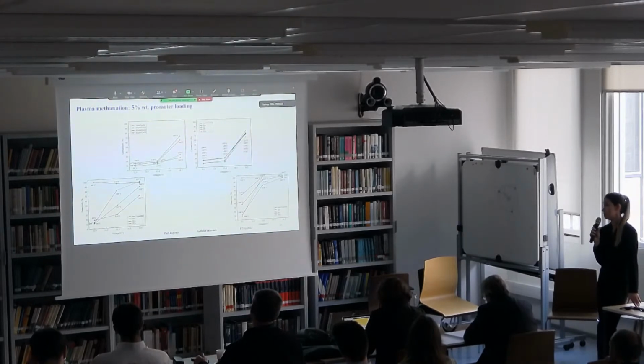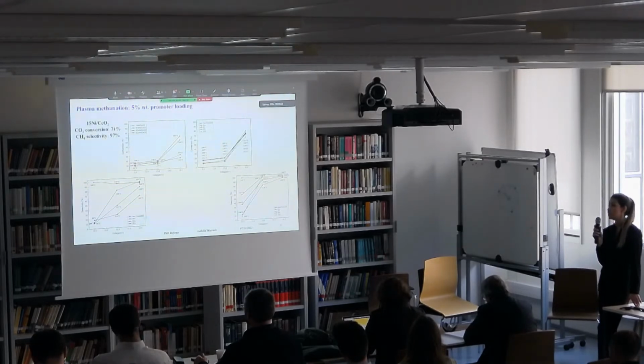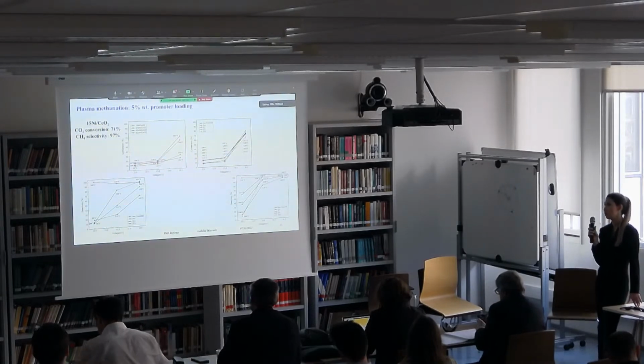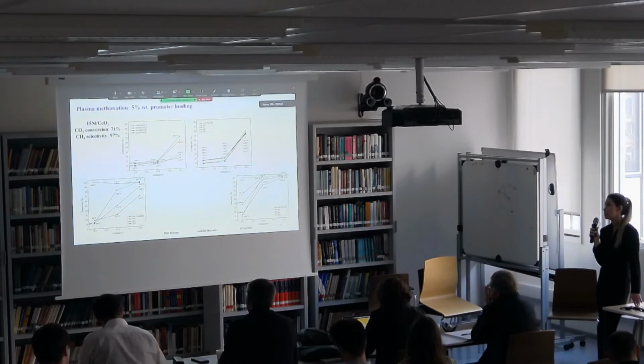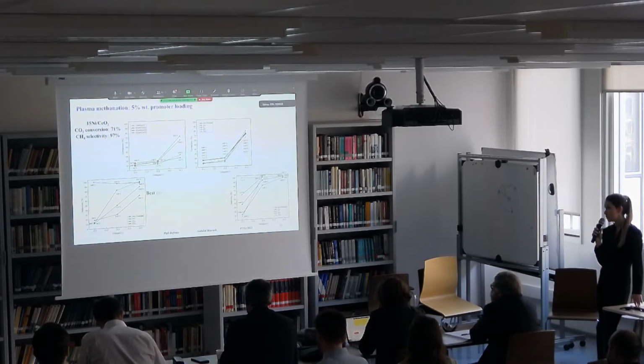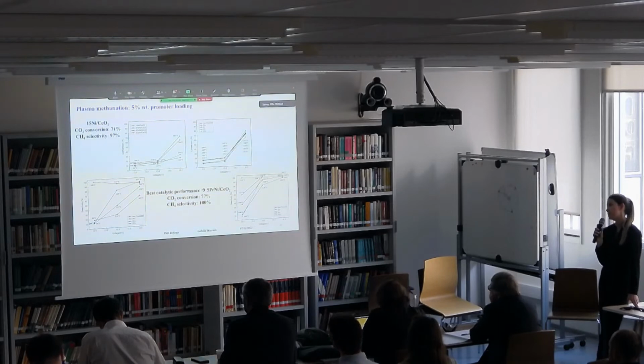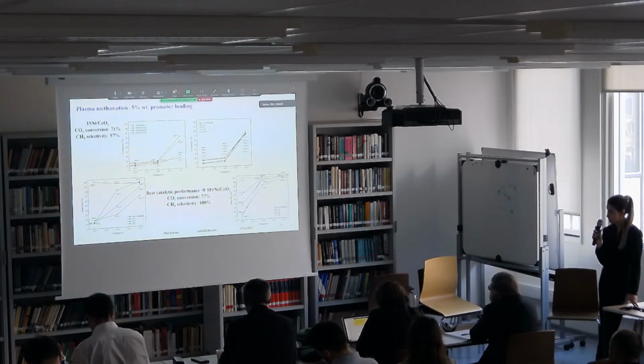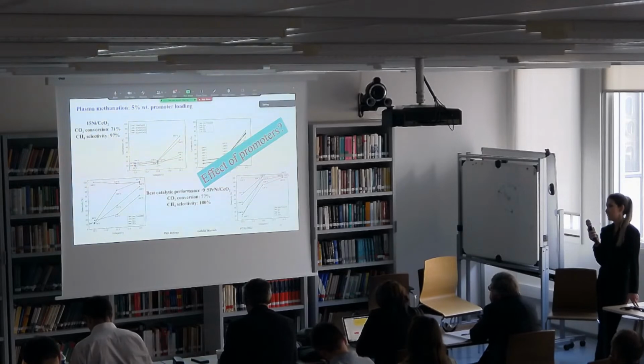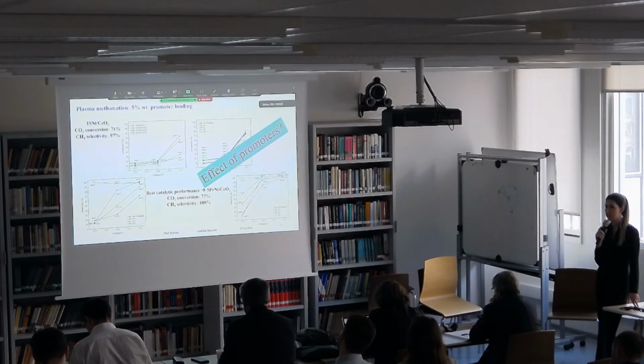Regarding the catalytic performance of the promoted samples, it was said that the non-promoted sample has 71% CO2 conversion, while praseodymium, lanthanum, and yttrium have a slightly higher CO2 conversion, with the best catalytic performance for the praseodymium promoted sample. But as you can see, there is no really high activity increase with the addition of a promoter. So it brings the question to mind: if they do not really increase the activity, what is the effect of promoters?